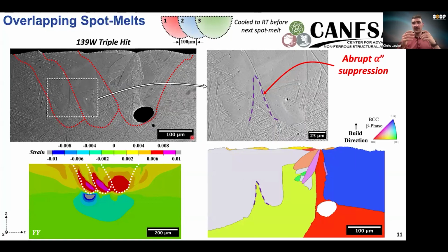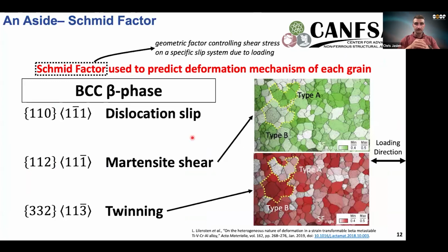So when we think about that in the materials community, that signals to us that there's some sort of orientation effect of these grains that are allowing a transformation or suppressing a transformation. So essentially, what that mechanism is called is the Schmid factor, which is a way to determine, based off of a specific crystal plane in your material, how easy it is going to be to transform